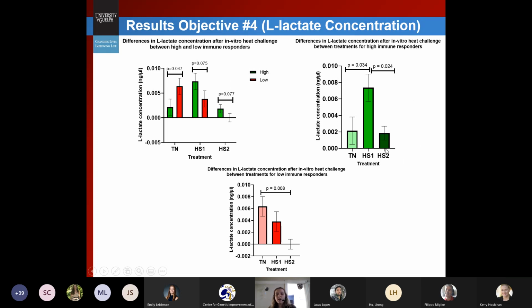And then looking at results within phenotype across the treatments, we see that at heat stress, our highs do have a significant increase in lactate production compared to at thermoneutral, but then we do see a significant decrease from heat stress 1 to heat stress 2. And then in the lows, we're seeing from thermoneutral to heat stress 2 a significant decrease in lactate concentration.